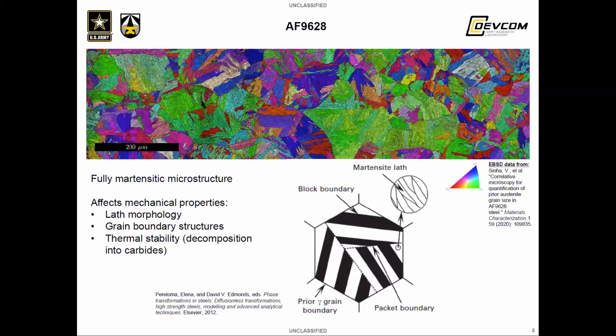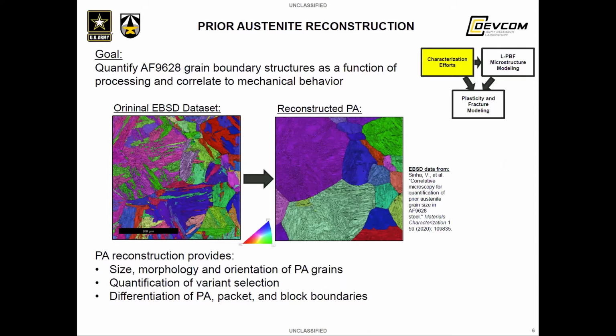Ultimately, the strength of this material is derived from the distribution of those different boundary types, the boundaries between laths, blocks, packets, and even prior austenite boundaries. And so characterizing and differentiating those boundaries is an important thing to do in martensitic steels and in this material in particular. So to characterize the material as a function of processing, one useful computational technique that I'll introduce now is prior austenite reconstruction. This is a computational method of grouping those martensite laths back into their parent austenite grain structures.